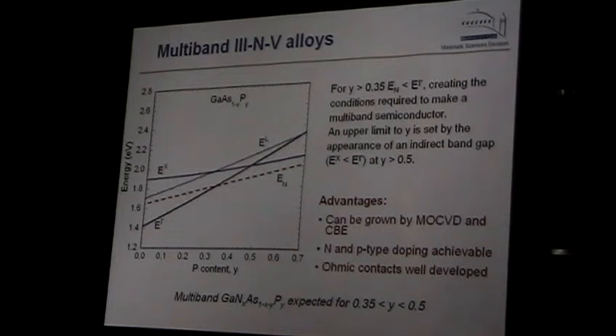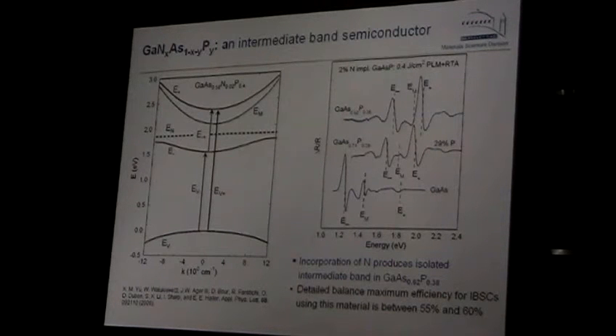However, as a first try to see if we can find the proper composition of the gallium arsenide phosphide, we did the same. We implanted 2% of nitrogen into gallium arsenide phosphide with different compositions. So we have gallium arsenide, this is our normal material. Now we add 29% of phosphorus, and then 38% of phosphorus. So now in gallium arsenide we have this lower band and upper band. Everything shifts up because if you have phosphorus, all the band edges shift up. But we see that this transition still remains, and in fact the intensity of the upper transition is becoming stronger, because this is our impurity band, or nitrogen band in this case, and this is kind of a regular band.